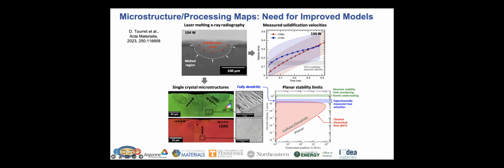And if we look, in this case, we're actually looking at these little dashed black boxes here. This is really at the melt pool edge. We see our planar zone that then transitions to our columnar dendritic zone. And clearly in both cases, we have a dendritic microstructure that exists after these solidification experiments. If we go and we think about that in the context of existing solidification models, and we do some sort of traditional classic types of predictions, it would predict that we actually would have reestablished a planar interface. And clearly we see still the presence of dendrites.